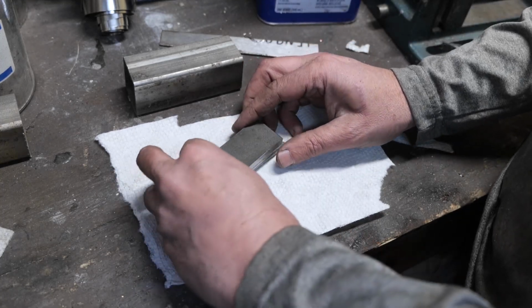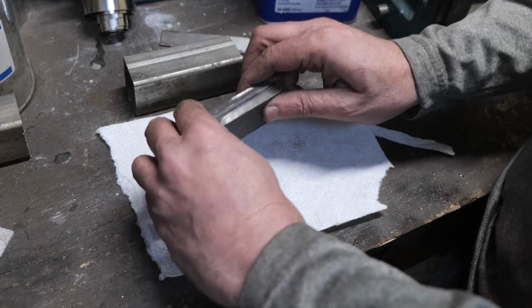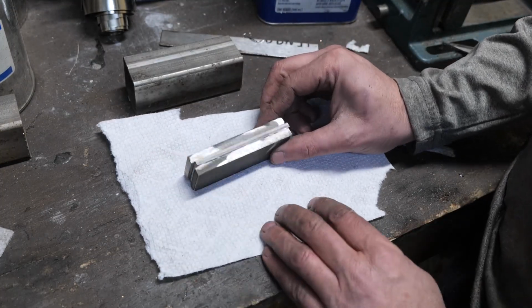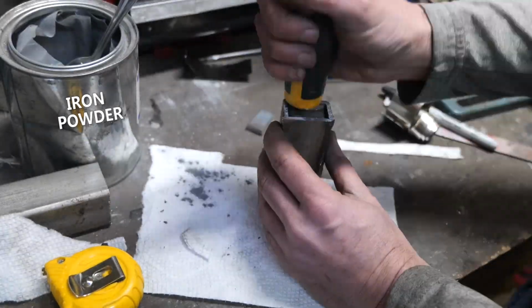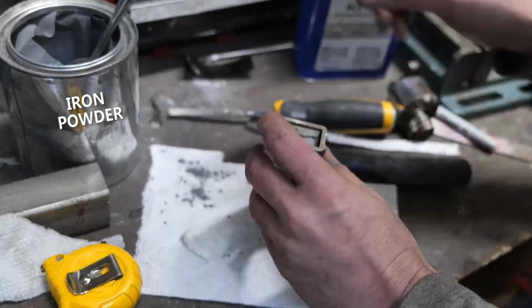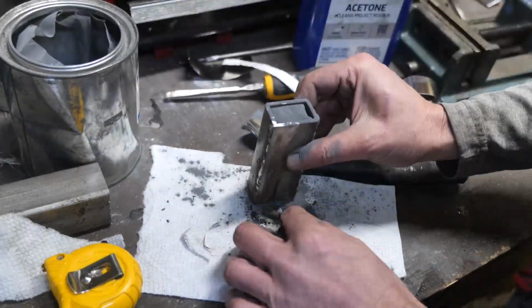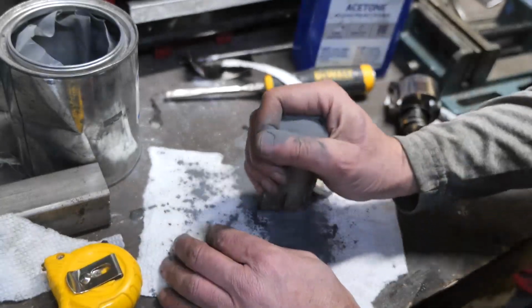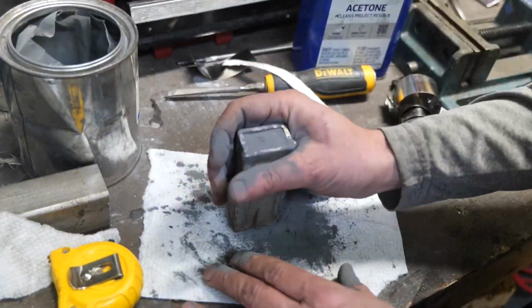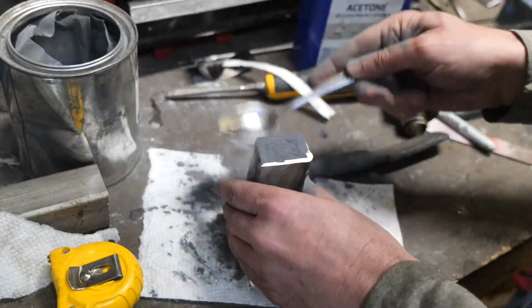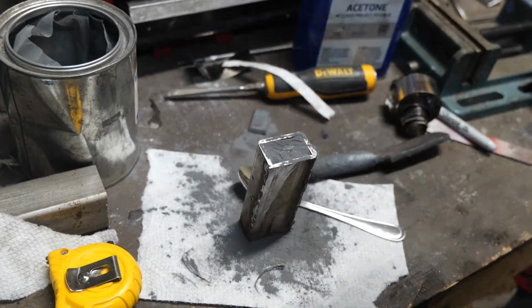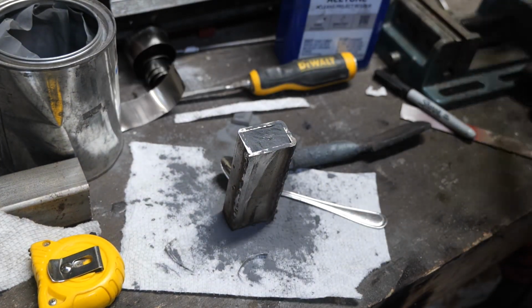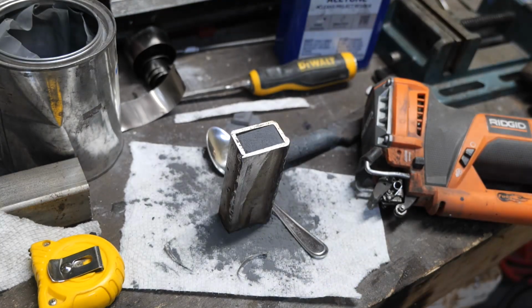The idea with the nickel sheet is that it should provide a more gradual transition zone, and some people think it welds to stainless better than carbon steel. I ground all the surfaces to 120 grit, then tack welded them together at the corners, which I ground flush before putting in the stainless steel canister with a bit of paper at the bottom. I'm filling in the tiny gaps along the sides with iron powder to get absolutely as much air and oxygen out of there as possible.